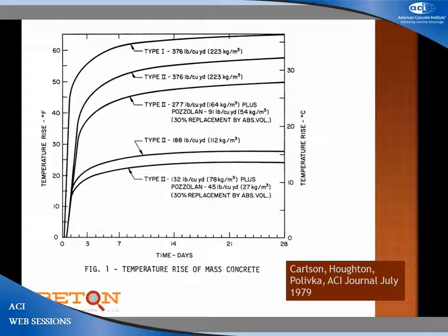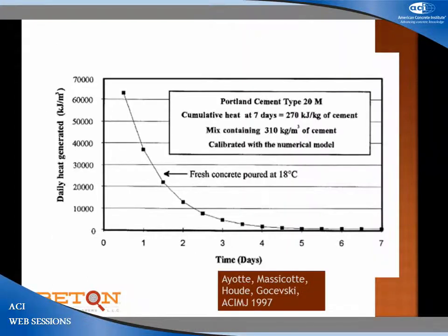And it's very useful. Then, keep going, 1997, another bunch of fellows building dams in northern Quebec said, hey, here's the amount of heat that's evolved, the enthalpy of reaction, per time. And you can see it decays exponentially because after about 4 days, it's in diffusion control. That's why he doesn't have any numbers up here, because it's way crazy up there.